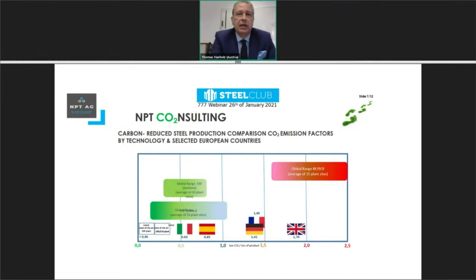Here is, I think, a very interesting slide where we had a look into the global range of tons of CO2 per ton produced. And here we can see that the global range of blast furnace BOF plants is between 1.4 and 2.5, depending on the age of the plant and the way the raw materials are used. The global range of electric arc furnaces for sections is between 0.3 and 0.7, and the pure electric arc furnace range is between 0.2 and 1. And if we look at it in terms of countries in Europe, we can see that the typical mini-mill countries like Italy and Spain are clearly lower in CO2 footprint, which is also a certain advantage in terms of costs for the CO2 certificates. Next slide, please.